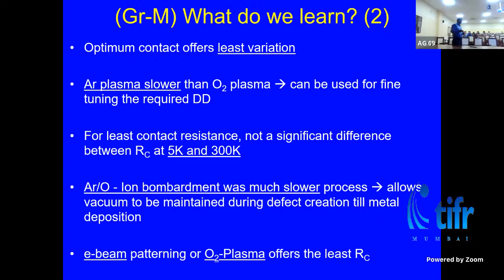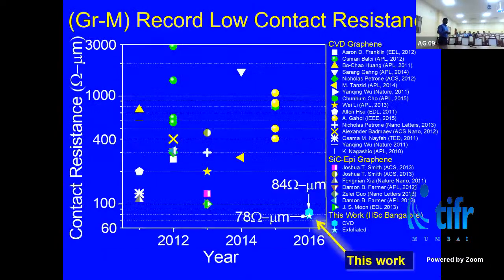And one more thing I've noticed is that the difference between the contact resistance at room temperature and 5 Kelvin also reduced. So when you have an engineered contact, this difference that you measure also reduces, because now it's purely depending on the channel and not something else, right? And I told you that the e-beam patterning or the oxygen plasma offer the least contact resistance. So this is the comparison. Our record low numbers were 78 ohm micrometer or 84 ohm micrometer, depending on the case.